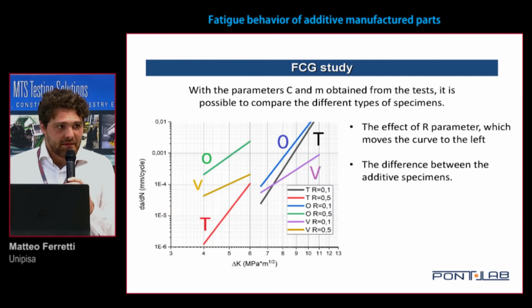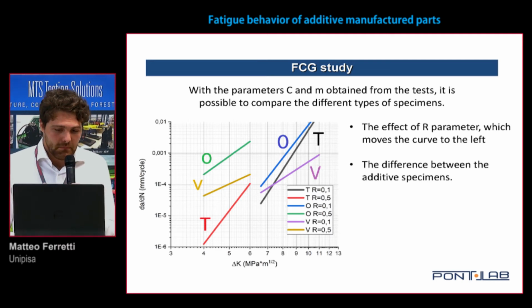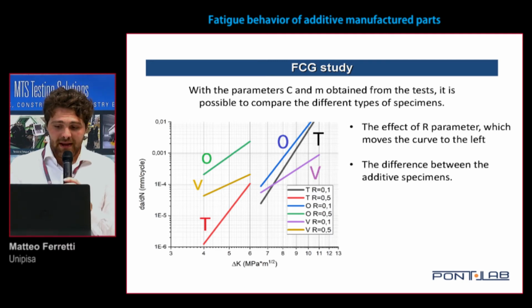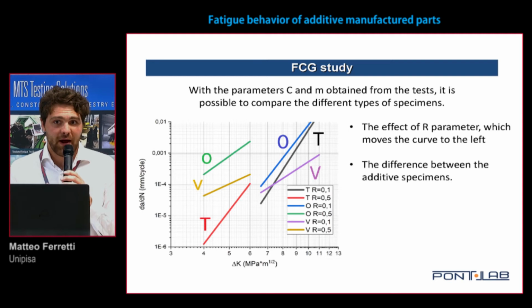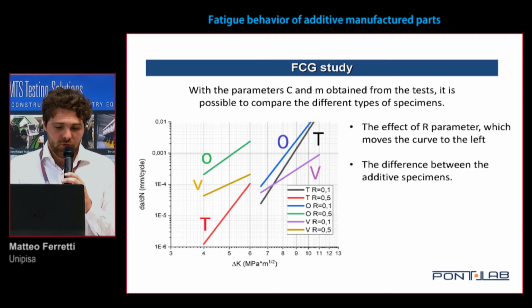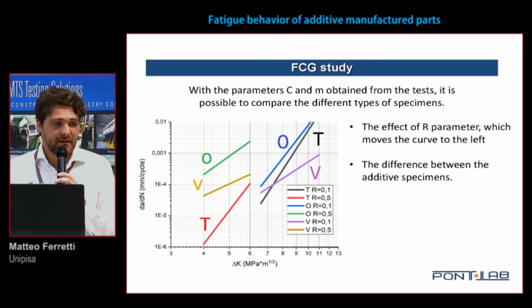With the parameters C and M obtained from the test, it's possible to compare the different types of specimens. It's important to identify the load ratio effect. Load ratio moves the curve to the left. The curve to the left is for load ratio equal to 0.5, and to the right is the load ratio equal to 0.1.